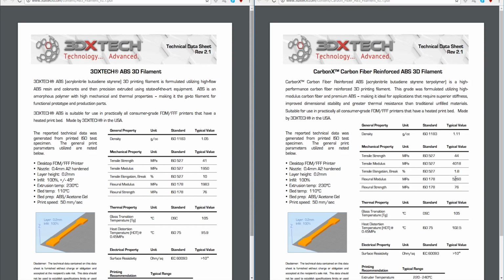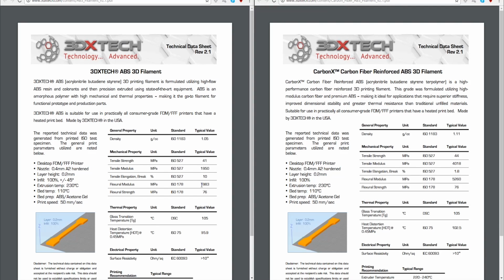Flexural modulus, almost times 3, maybe like what, 2.5? Yeah, a little bit over 2.5. So a little bit over 2.5 times the tensile modulus there. Here, 2.5 times. Flexural strength, identical. So you're limited by the matrix of the piece. Doesn't really change the glass transition temperature. A little bit here. Right, so a little bit increased stability.